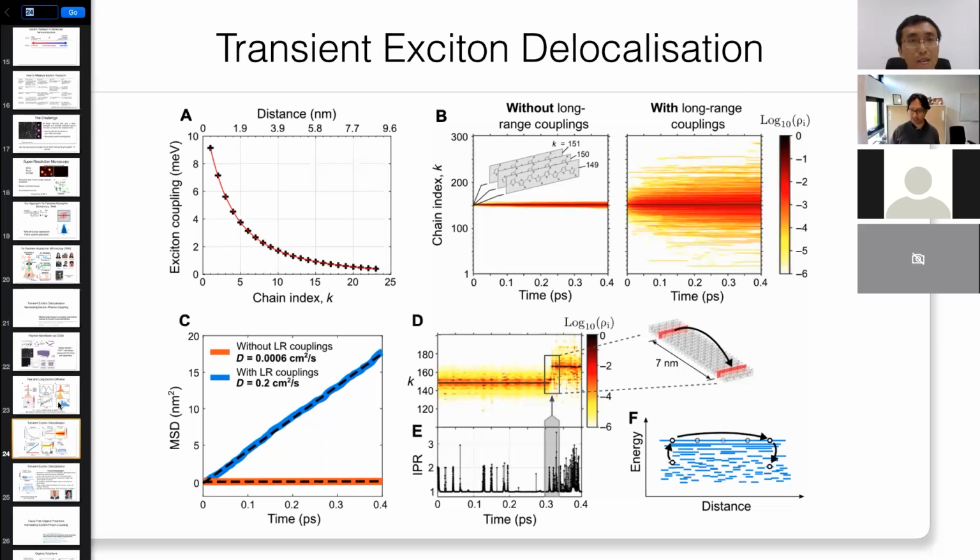Yeah. Something that is not widely appreciated is that the high frequency modes in organic systems are zero-point quantum motions, right? They're not thermally populated phonon modes because the energy is too high to populate thermally at room temperature. Room temperature is 25 meV, these modes are 180 meV, so they're not thermally populated. So these are all zero-point quantum oscillations. It's a purely quantum mechanical phenomenon. You can't explain it in classical systems because you wouldn't even have these molecular motions if it was a classical system. These zero-point quantum motions around those vibration modes are what's coupling the exciton. So it's definitely a completely quantum effect.